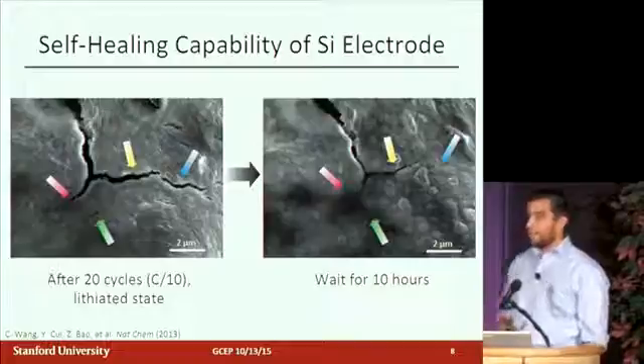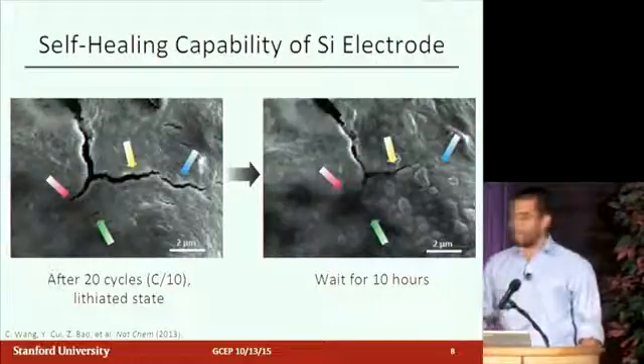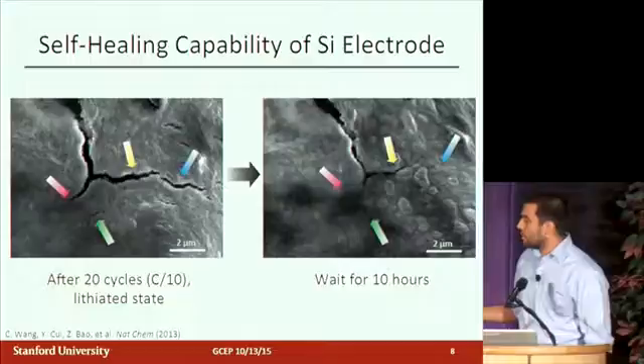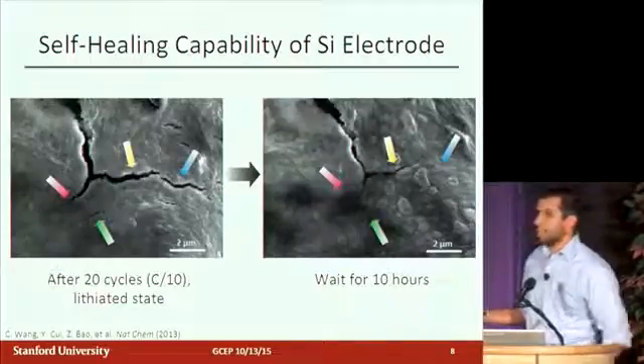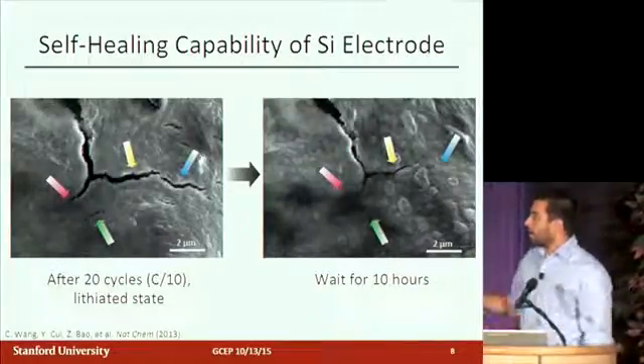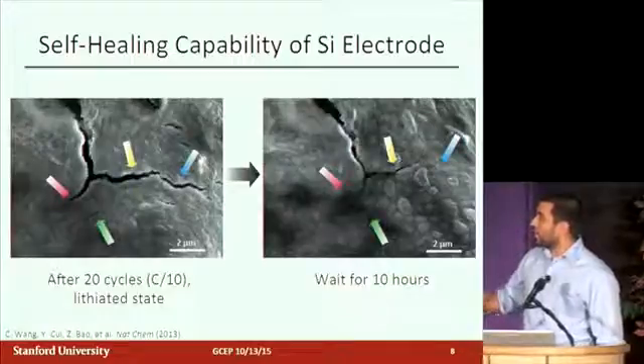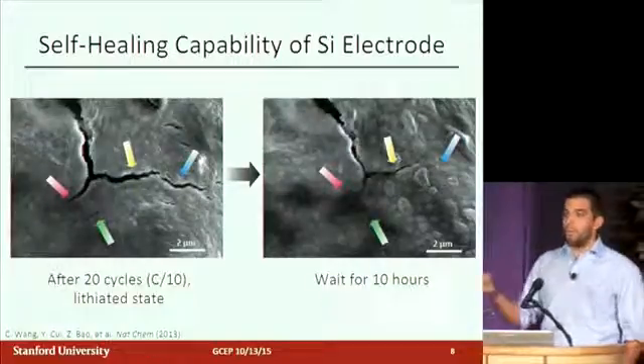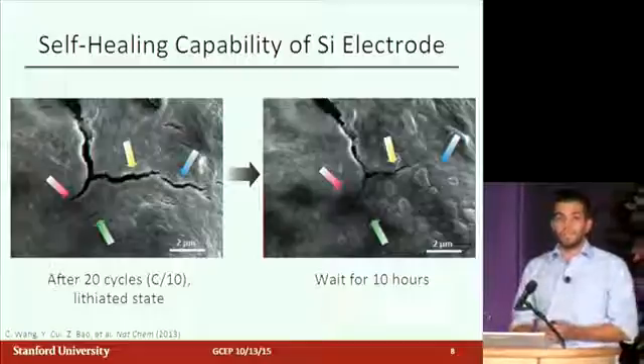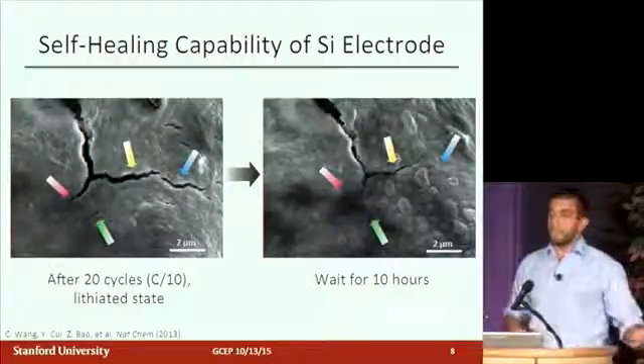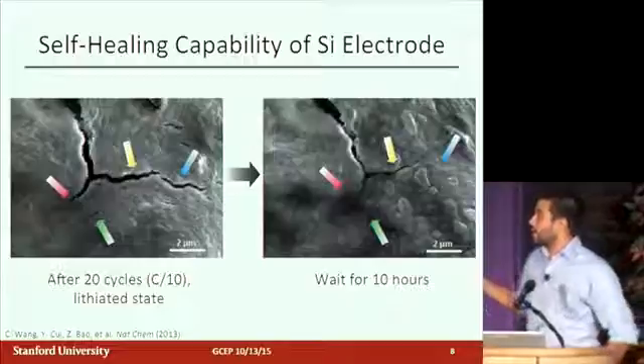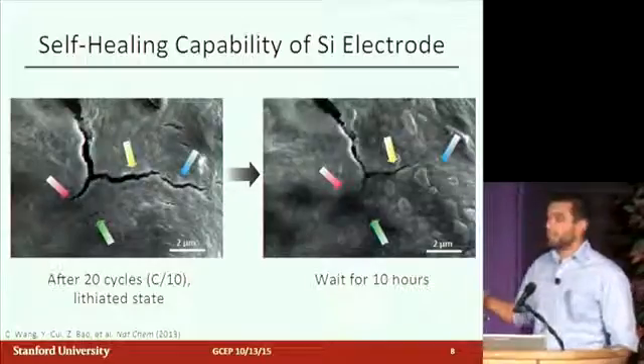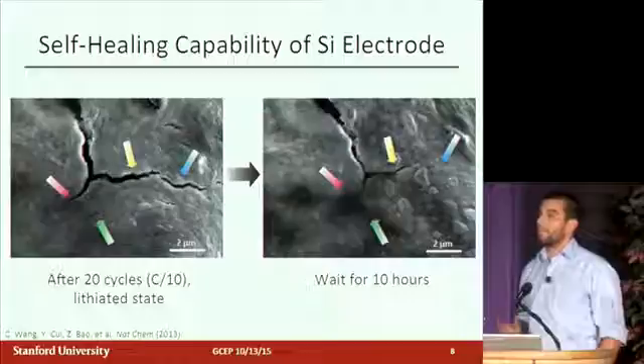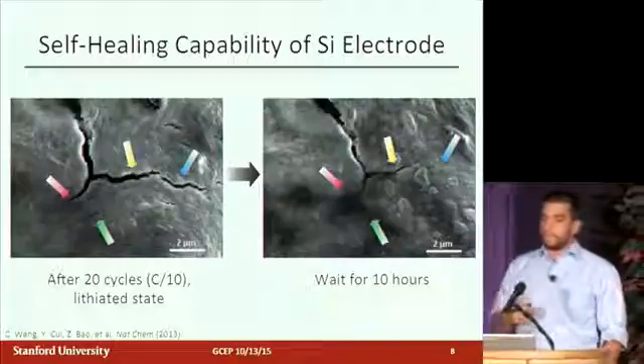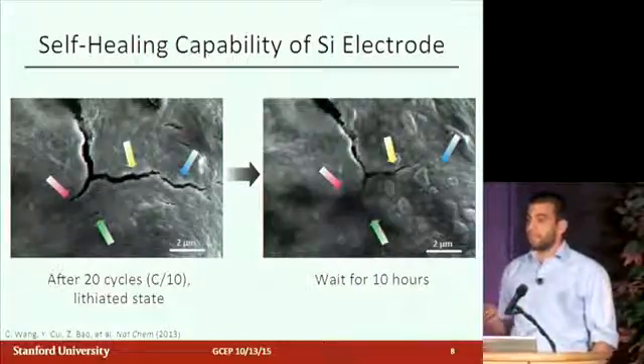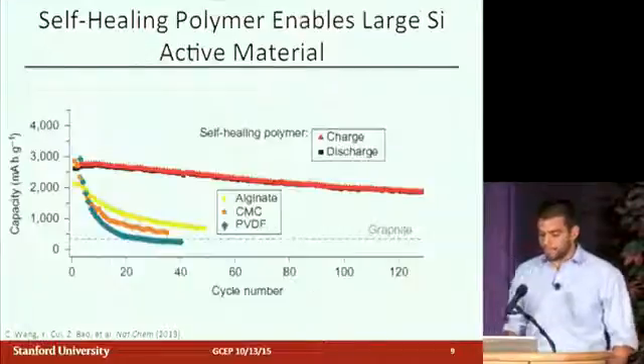We wanted to check this out just to be sure it was doing what we thought it was doing. And so here are some SEM images. This is after 20 cycles in the lithiated state, so in the expanded silicon state. You can take it out, and you see there are some really large cracks in the electrode that form, which is what we would expect in a material that has expanded so significantly during cycling. But then if we wait 10 hours, put it back in the SEM, and look at it again, we see that some of the smaller cracks have healed, and some of the larger cracks are smaller than they were before. And so we think this really illustrates that the self-healing mechanism is doing what we think it's doing.